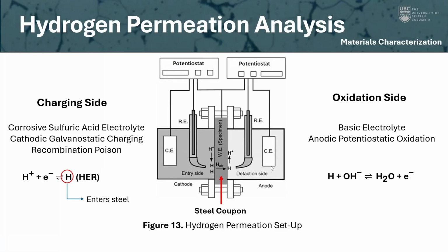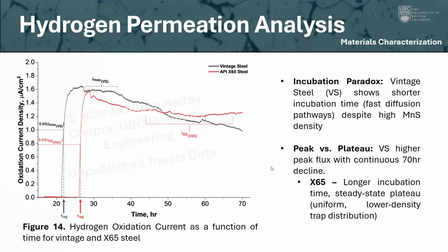Once that hydrogen adsorbs onto the steel, it diffuses through the membrane, where when hydrogen exits the membrane, it's immediately oxidized, and we impose a positive potential. And so this image just explains that setup. And from these results, we obtain these permeation transients, and we see two very different integrity stories. So this oxidation image essentially corresponds to, as soon as that hydrogen exits the steel, it's oxidized. And so that oxidation current refers to exited hydrogen, right?